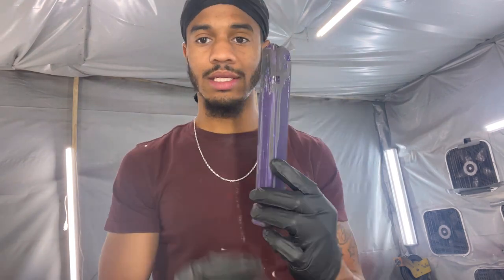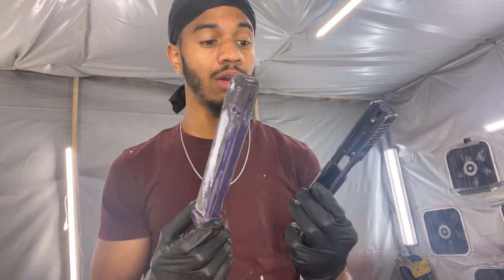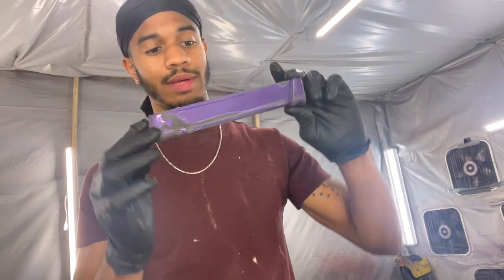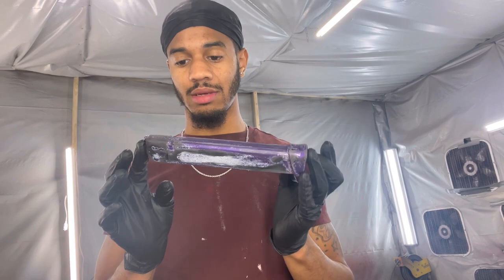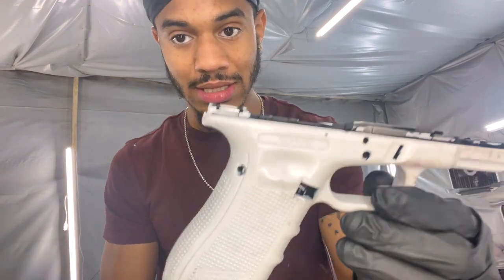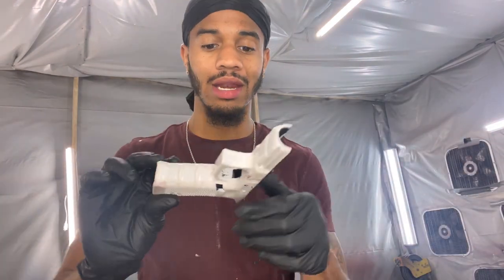Like this, as y'all can see, the red came right off, just slipped right off. And this was the House of Kolor red. I soaked all of these pieces, and literally it wasn't no more than 30 seconds to a minute, and that red slid right off. But this white is not budging. I mean, this got soaked in gun cleaner and lacquer thinner.